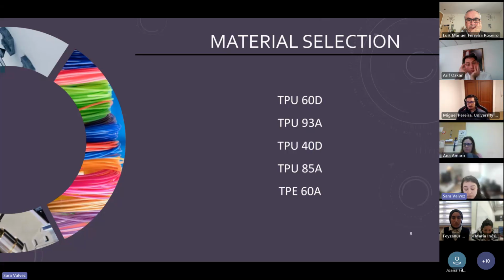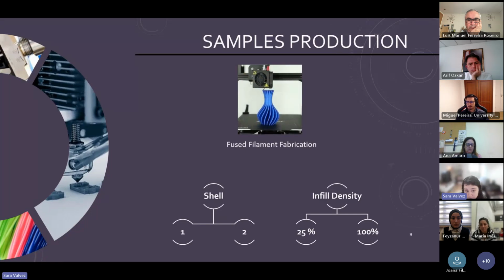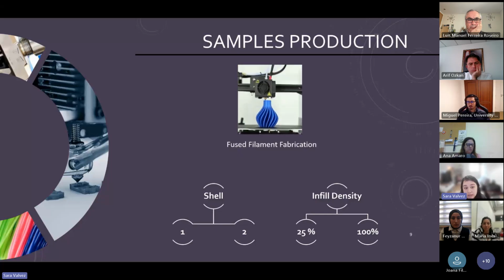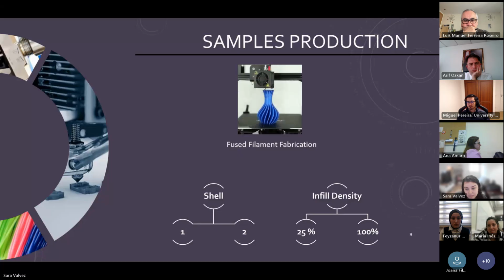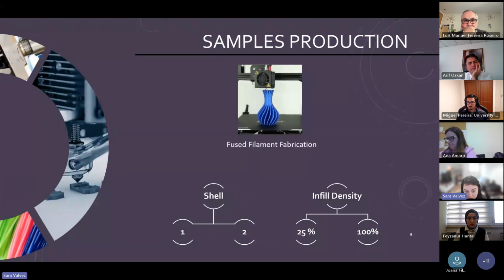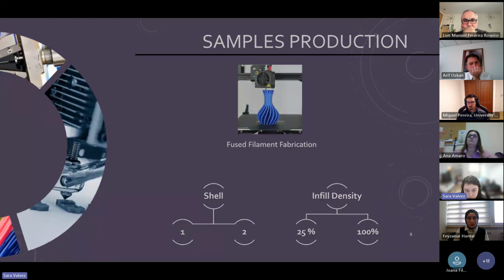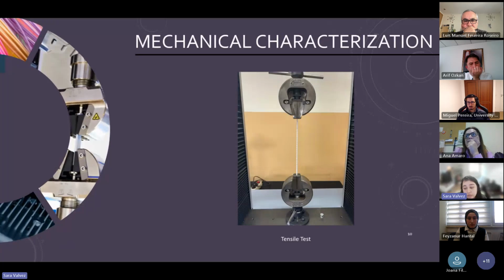We selected 5 materials with different hardness values. Then we printed the samples with those materials, using fused filament fabrication technology. The samples were printed with a grid infill pattern, and the second part of this research is to investigate the 2 printing parameters that have the most influence on the structural integrity of the specimens. So the number of shells, we use 1 or 2, and the infill density, we use 25 and 100%. And then the samples were characterized using tensile tests.